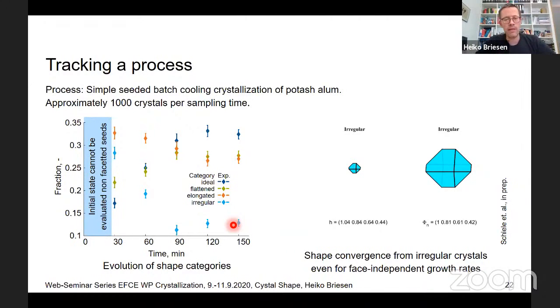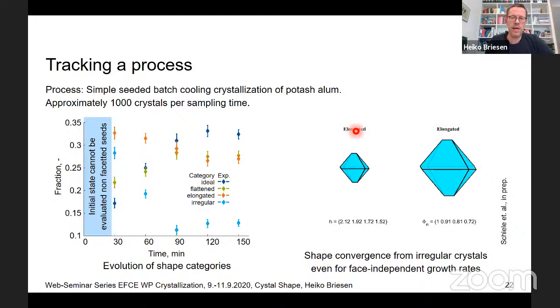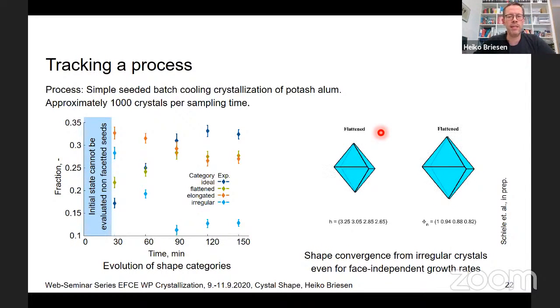You see here an irregularly shaped crystal as an initial value, and if you now just let this crystal grow with a face-independent growth rate, so each one grows identically, on the right side you see the size-normalized one. This one here is the non-normalized one, so this will actually grow, the other one will stay roughly the same. But you see that here, this is still the elongated shape, but this will then switch at some point to a flattened shape, and in the end, it will end up as an ideal shape.